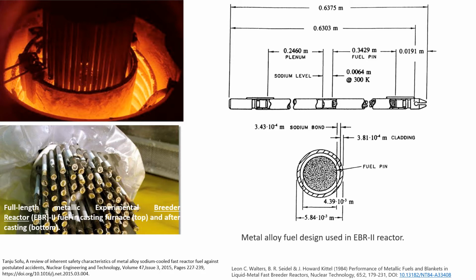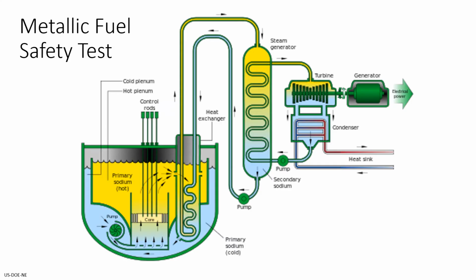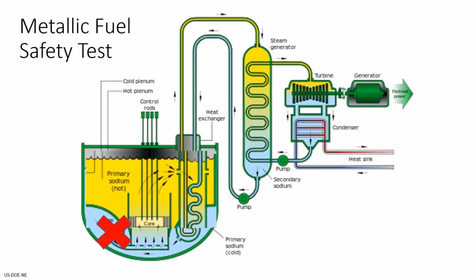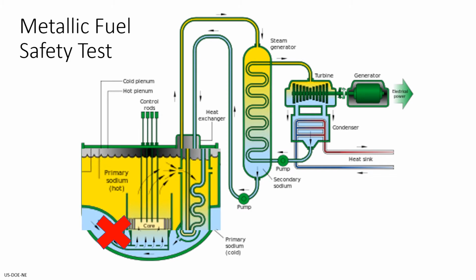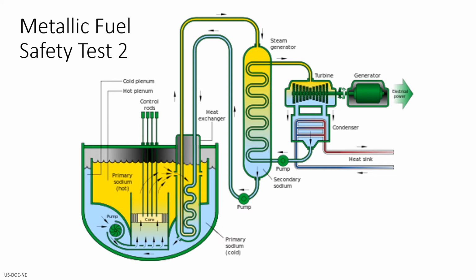Experimental Breeder Reactor II had 67% enriched uranium when fresh. It was alloyed to 10 weight percent zirconium, and the long fuel rods were inserted into thin stainless steel cladding along with liquid sodium for the fuel pellet and cladding gap. Two impressive metallic fuel safety tests were conducted using this special reactor. Firstly, they shut off the main coolant pump at operating conditions, which was 62.5 megawatts thermal, bypassing normal safety features. The core dropped to near zero power within 5 minutes due to the negative temperature reactivity coefficient of the fuel, combined with the thermal expansion of liquid metal coolant.